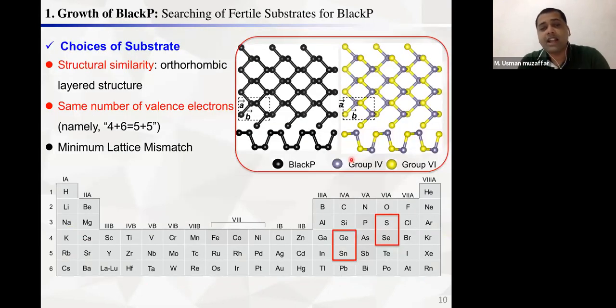For this standing challenge, this time we propose a straightforward yet conceptually intuitive approach with three guiding principles. First is the structural similarity, and second is the isovalency rule. The third one is obviously straightforward: the minimum lattice mismatch. We know that black phosphorene has an orthorhombic layered structure. You can see from this figure, it's a layered structure with an orthorhombic lattice.